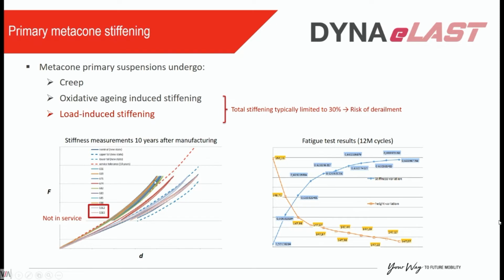But if you look at the ones that have been under cyclic loading, have been in operation, they've stiffened a lot more. They even go beyond the tolerances. I mean, this is not a problem. They were out of service because it's 10 years after manufacturing date, so they have to be out of service already. But this shows how this stiffening effect is actually something we see, we observe.